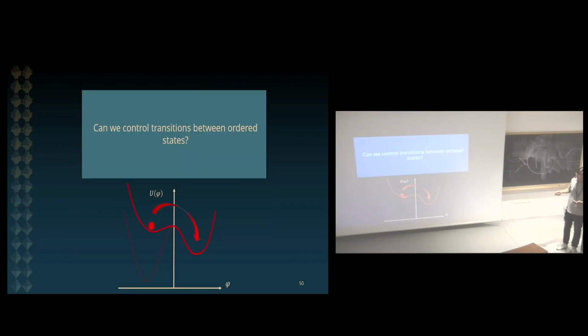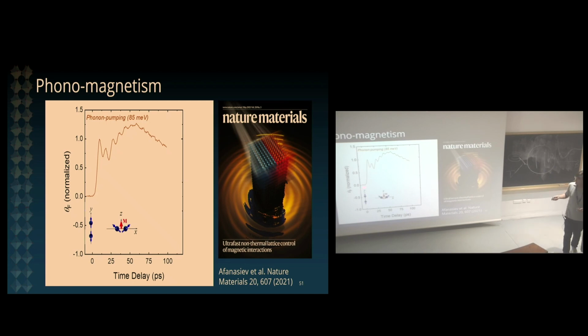So in principle, if we hit the system hard enough, maybe it's possible to go from one minimum to the next. And that's what we are showing in this measurement here. This is again the Faraday rotation versus time. At equilibrium, there is no Faraday rotation. The system has no net magnetization. But when we hit the system with a strong laser pulse, the system starts to develop a net magnetization. You see that it starts to oscillate, but now it doesn't oscillate around 0. It starts to oscillate with a finite net magnetization.